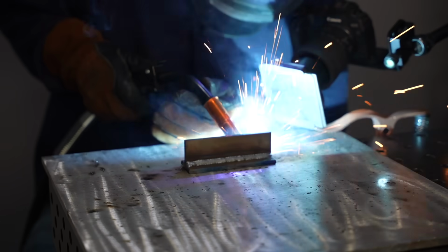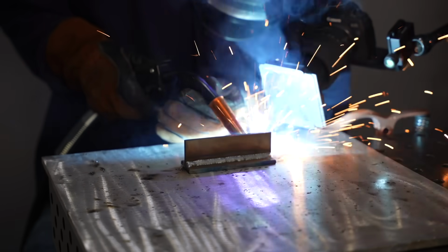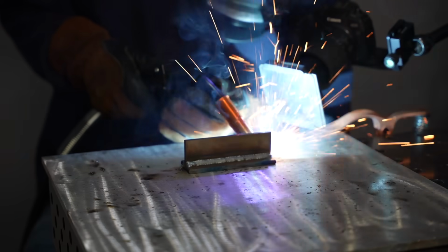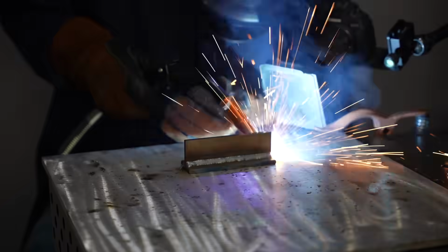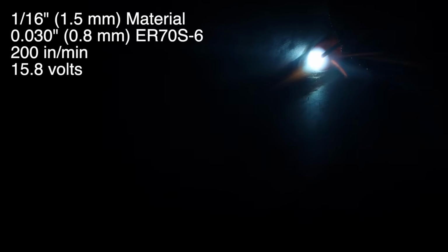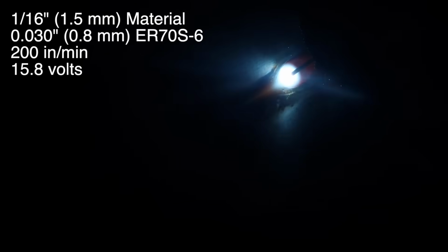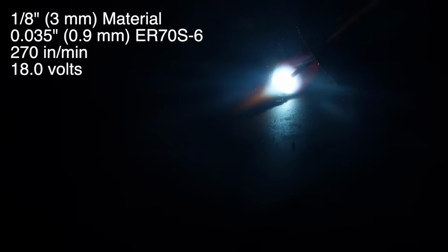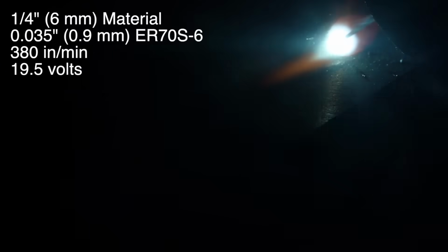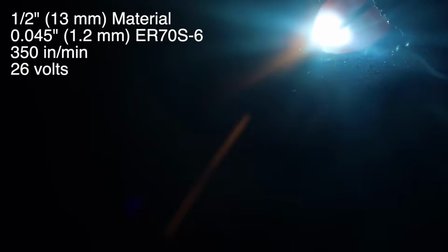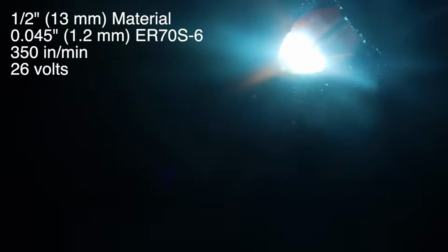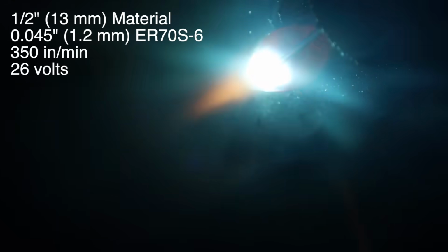There's a really wide range of material thicknesses you can weld with a given wire size, but here are my picks for the ideal. 1/16th to 1/8 inch thick, I'd say run 030 wire. From 1/8 to 1/4 inch thick, run 035. And over a quarter inch into half, I'd say go for 045 if you have a machine that can push enough amperage.